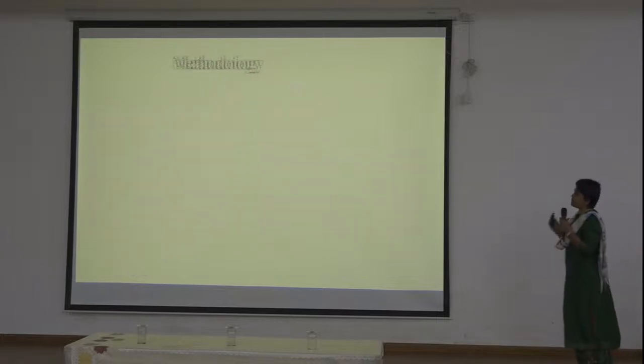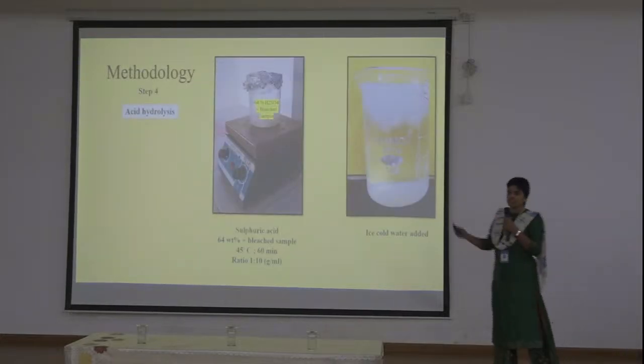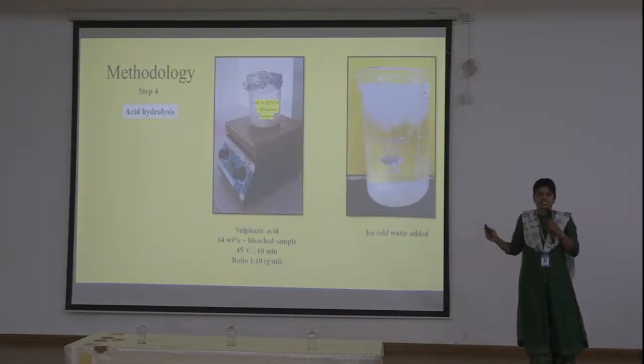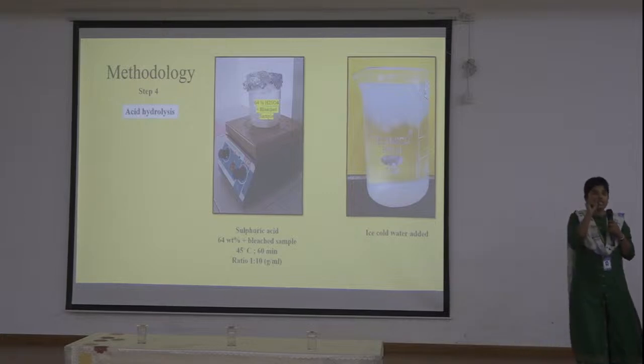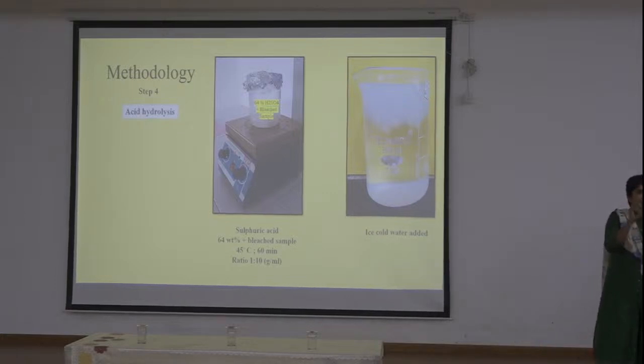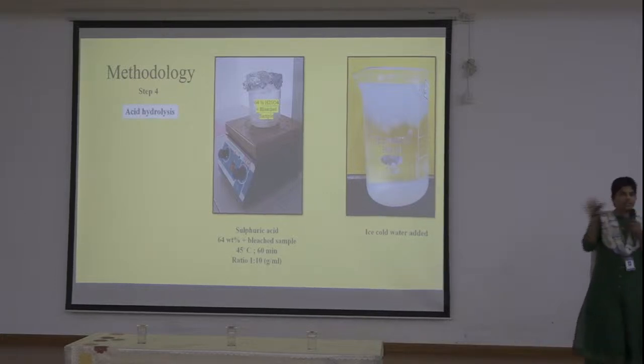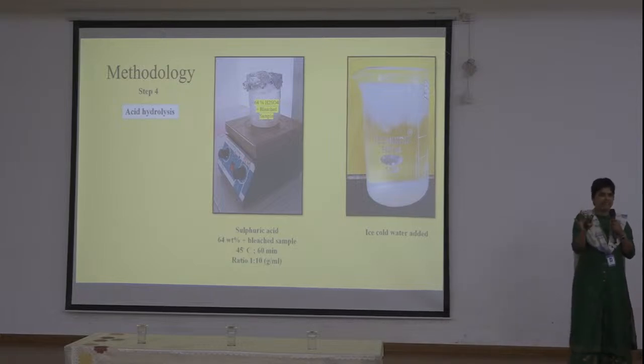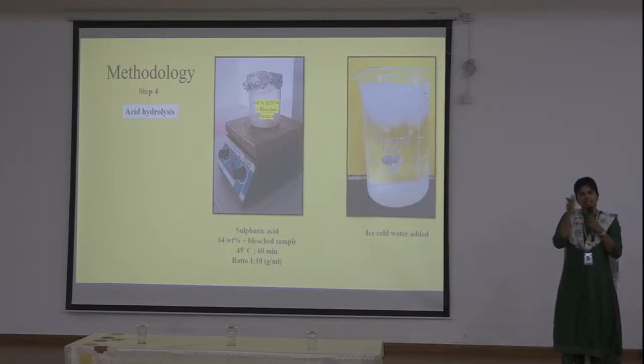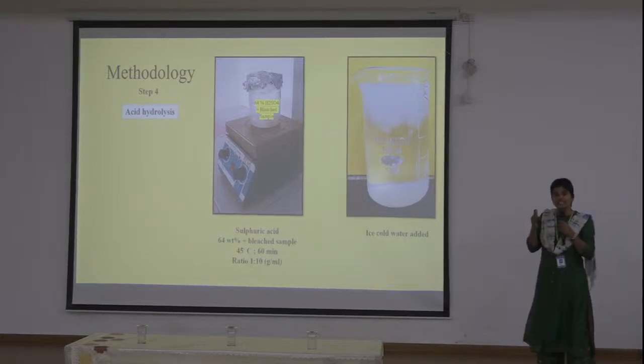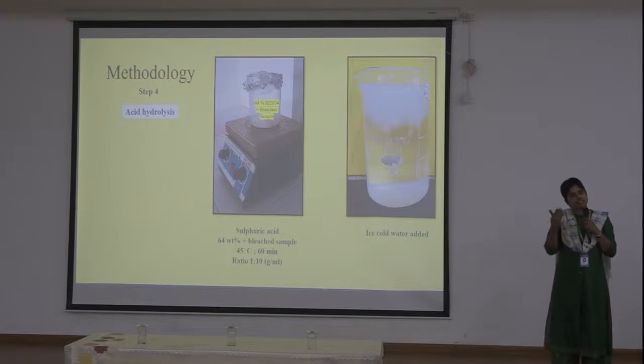This bleached sample is taken for acid hydrolysis. The acid I used is concentrated sulfuric acid. Cellulose has two regions: amorphous and crystalline. We don't want the amorphous region because it doesn't have crystalline properties. The crystalline property lies in the crystalline region, and this is necessary for the reinforcement agent.